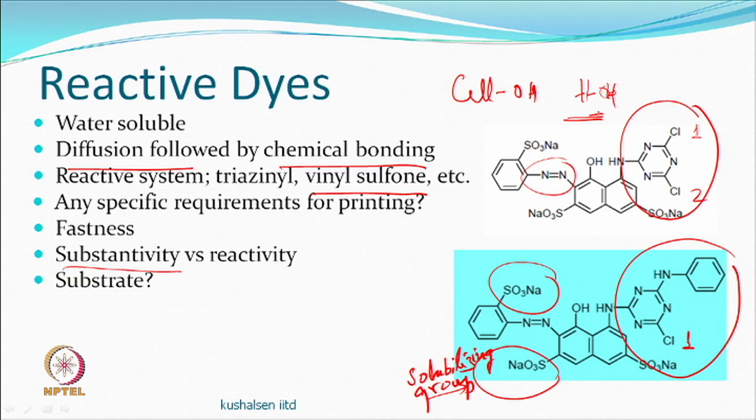The end amino groups are good enough to react and do not require alkaline medium. And if you do not require alkaline medium, the hydroxyl group, that is water, will not react, and therefore you will have less hydrolyzed dye. So for the protein fibers, a different pH is a much better option, and the reaction takes place.